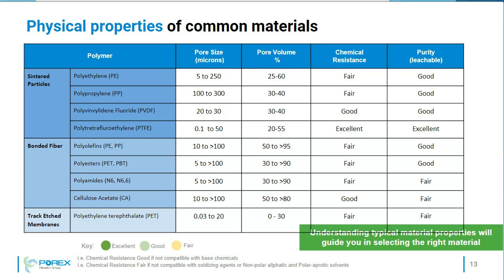So just for reference, when you're looking at that pore size, the information presented there is taken from a number of measures. What we do is we take a bubble point testing method to determine the largest pore size in that porous media. And then we go to the mercury intrusion test to capture a median pore size. That's how we capture a range. And you would work with your supplier to determine the actual tolerance you're looking for in the pore size. And we do the same for pore volume, densities, and so on and so forth.